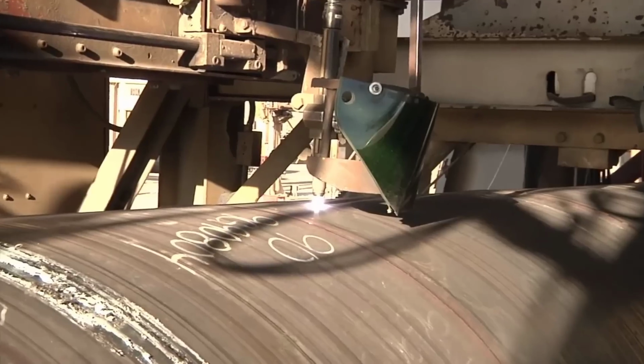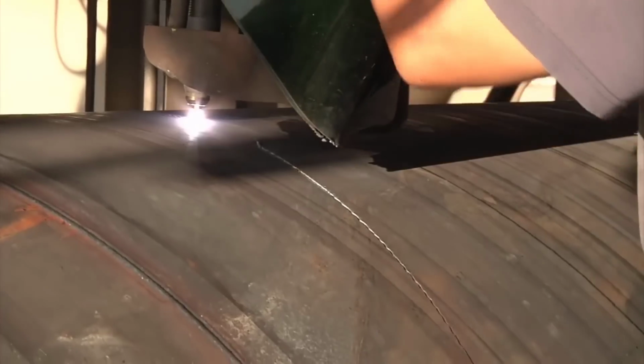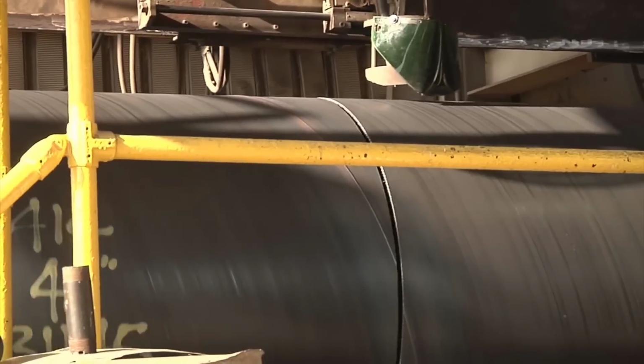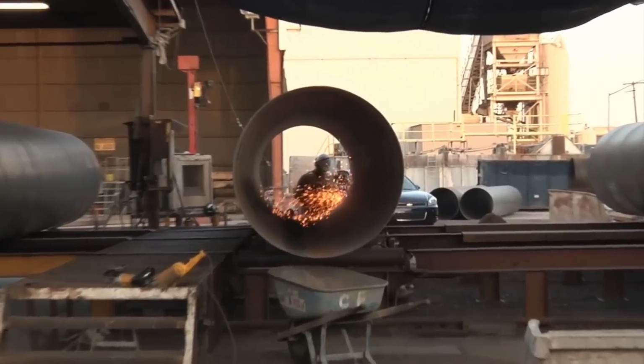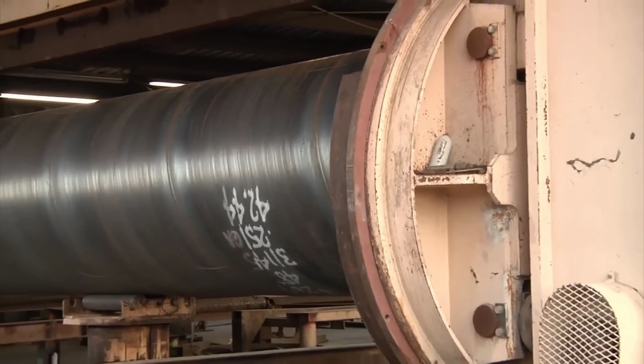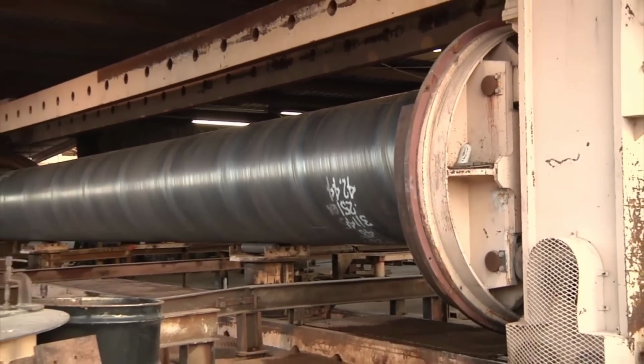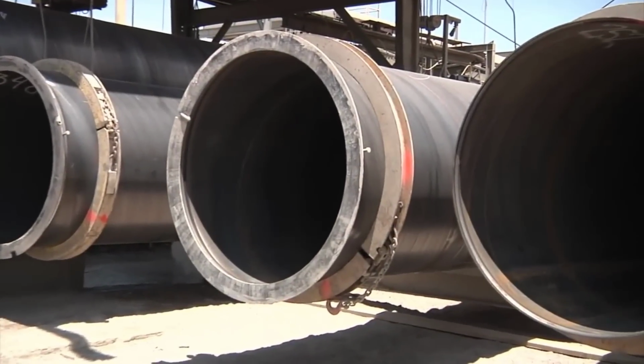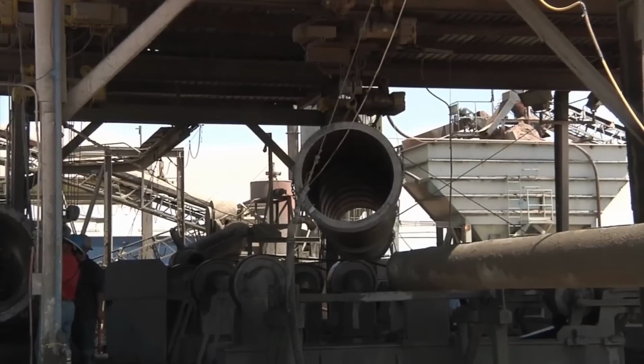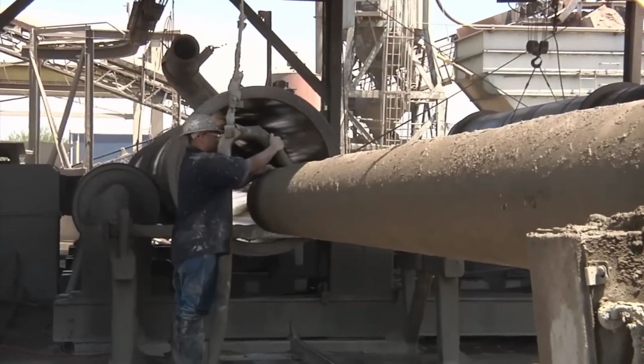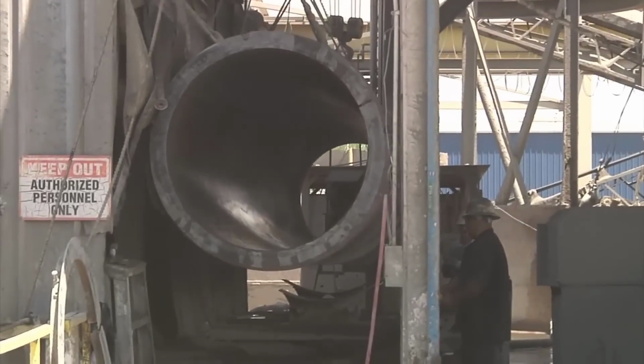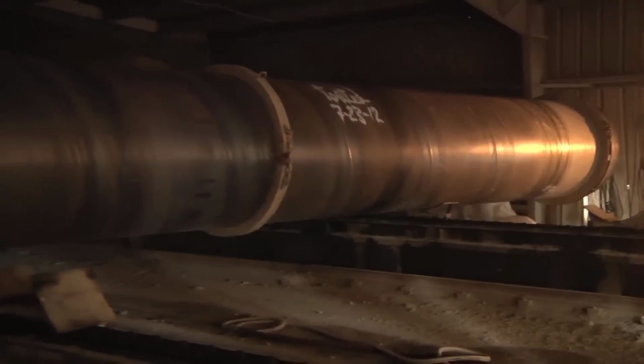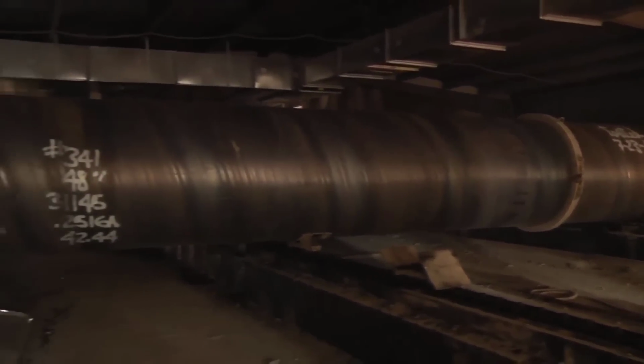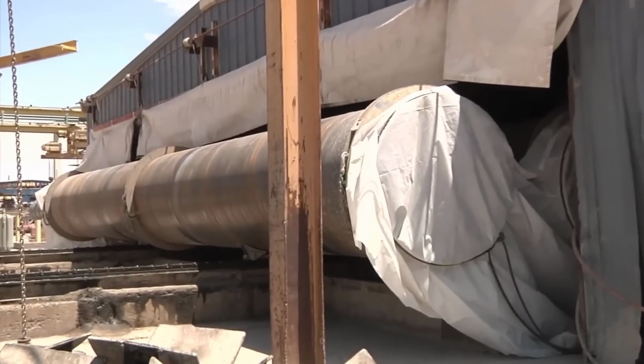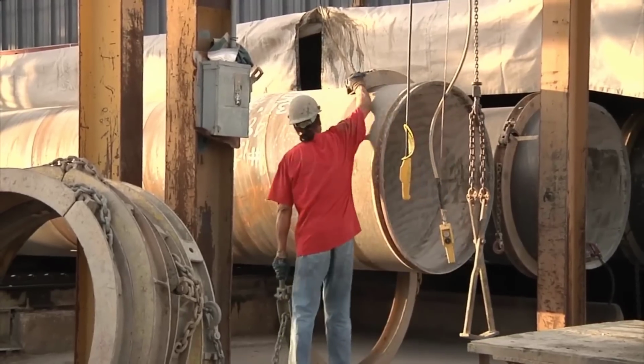Stiffener rings are placed around the cylinder to ensure roundness before it is transported to the lining area. In the lining area, a mortar lining is applied using a centrifugal process. After this, the pipe is placed in a cure cell for elevated temperature curing with steam. Once curing is complete, the stiffener rings are removed, and the lined cylinder is prepared for the final stages of the process. Unlike C301, which uses pre-stressing wire, C303 is wrapped with mild steel bars.